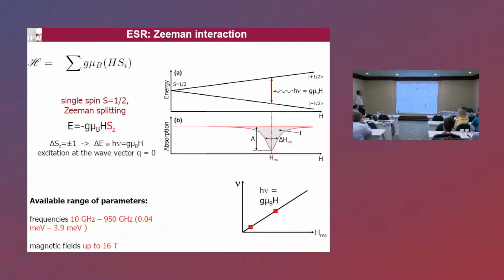Actually, the principle of electron spin resonance spectroscopy is very simple. If one has a spin one half particle, in zero field the two possible energy states, spin plus one half and minus one half, are degenerate. One applies an external magnetic field and splits these two states according to the Zeeman effect. If one shines electromagnetic radiation of appropriate energy, which meets the gap between these two split states, the electron spin system will absorb the energy and give rise to a resonance signal. One can change the excitation frequency, and correspondingly the resonance field will change.